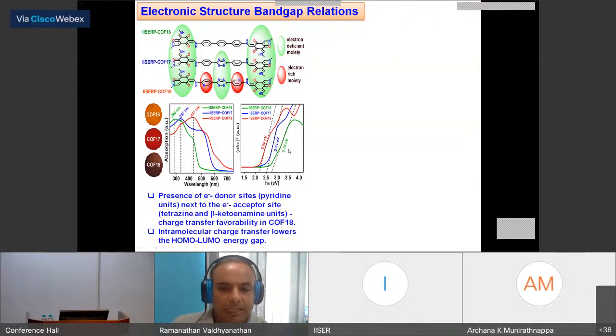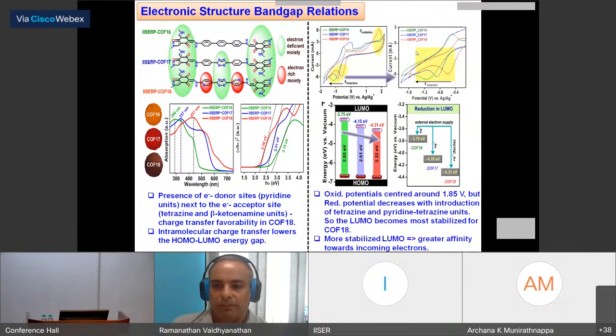and you can see the HOMO-LUMO gap is systematically decreasing as we go from the all carbon to the only tetrazine to the tetrazine plus pyridine groups. And this is also beautifully seen from the cyclic voltammetry, where what you see here is the oxidation curve and the reduction curve. You can see that for the oxidation potential, there is no shift in the peaks, whereas at the reduction, there is a systematic shift as you go from all carbon to the tetrazine to the tetrazine plus pyridine, and the shift is in a potentially favorable direction, which means as you introduce pyridine plus the tetrazine into the structure, the LUMO levels are decreasing, whereas the HOMO level remains the same. And that is what is shown here. The HOMO level is remaining the same, but the LUMO is decreasing systematically.